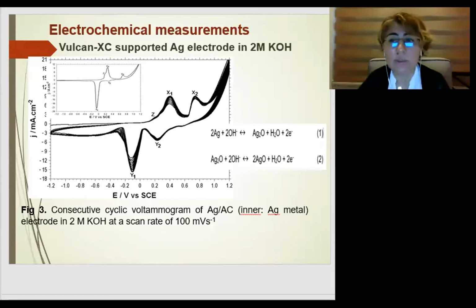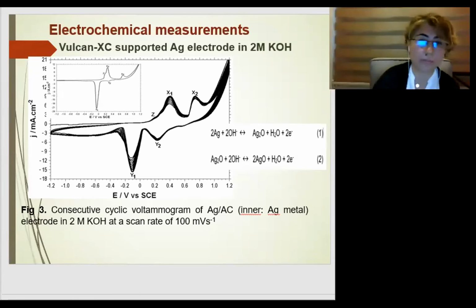The observed increase of the current peaks of the cyclic voltammogram for the later cycle is caused by an increase of the surface roughness during the first oxidation-reduction cycle. In this case, at the potential of pre-peak Z, you see here, several monolayers of silver(I) hydroxide are formed, and above them a thicker, more porous layer of silver oxide grows.